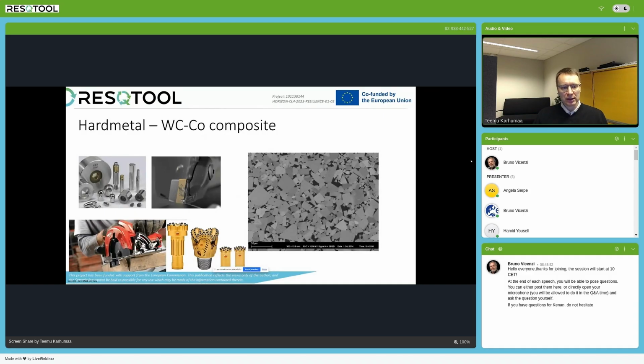Cold forming tools, wire drawing dies, metal cutting tools in the form of inserts or drills and end mills, and then tools for woodworking, concrete drills, and stone drilling in the mining area where holes for blasting, for example, are needed, and then also some tools in the gas exploration in the energy industries. And on the right side, you see a typical picture of hard metal microstructure consisting of these light gray particles of tungsten carbides, and then in this case the black phase, which is the cobalt binder in between the grays.